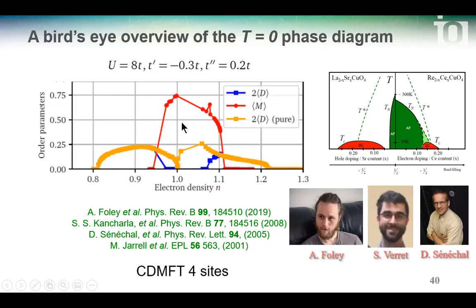So this is a phase diagram that was found by the group of David Sénéchal, Alexandre Foley and Simon Verret. You see that this is the order parameter that characterizes superconductivity, and electron filling here on the horizontal axis. So this is half filling, one electron per unit cell. So you see the antiferromagnetic phase in red that has this right asymmetric shape. And if you look at superconductivity, it follows the orange line. And then when it contacts antiferromagnetism, it goes down along this blue line. And similarly on the other side. So you see that it's not a bad start.